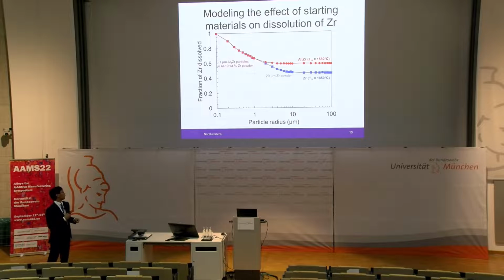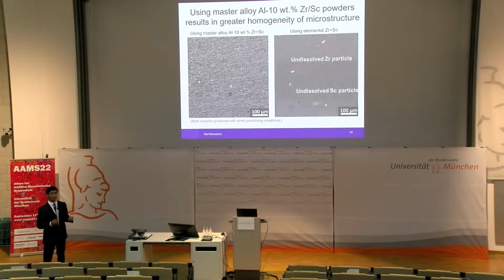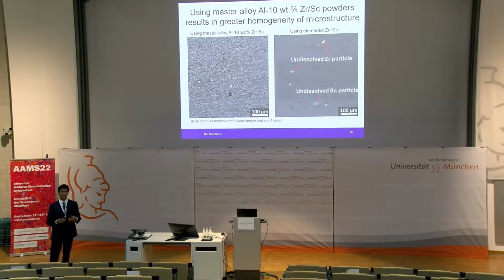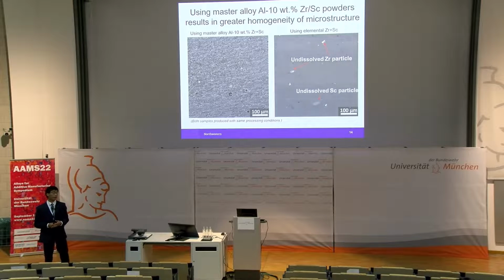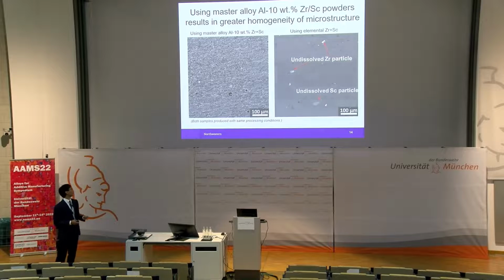So we revisit this process where we produce these master alloy powders. And by the way, we don't do this by atomization. Instead, what we do is we arc melt together pure aluminum and pure zirconium, and then pulverize this using a high energy ball milling process. So we produce these master alloy powders, again mix it with the pre-alloyed aluminum magnesium, and then print it.